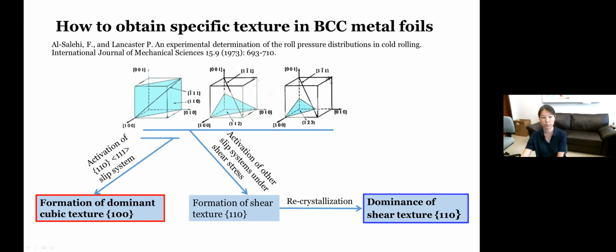Another common texturing that is known in the BCC metal is the shear texturing, also known as the Gauss texturing. To obtain the Gauss texturing, it is a bit more complicated than the cubic one because the formation of the shear texturing relies on activation of multiple shear systems, right? And bad news is that by using the shear stress, you would be only getting a certain amount of shear textures, but not all. But then the good news is that the shear texture grains, once formed, are associated with the lowest stress level and lowest defect density.